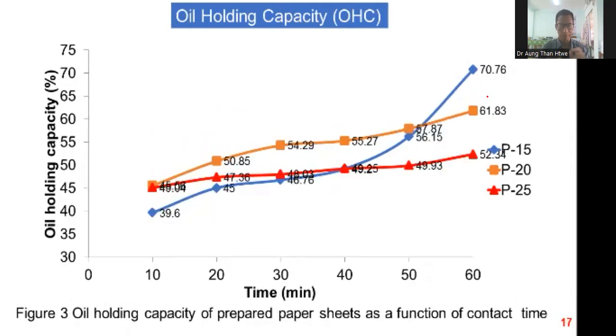Let me continue with the oil holding capacity. As in the figure, the oil holding capacity goes up from 39.6 to 70.76%. Similarly, the OAC values are also much higher than the more alkaline concentrated treated paper. Accordingly, the porous microstructure of paper has a bigger effect on OAC than its affinity for oil, which explains the OAC reduction with particle size decrease. However, the mechanism of the oil holding is more complicated than just porosity. It can be explained by the presence of oil on the external surface of the particle, which may inhibit or delay the interaction between the particle surface and water.